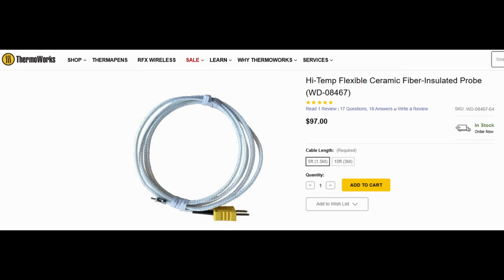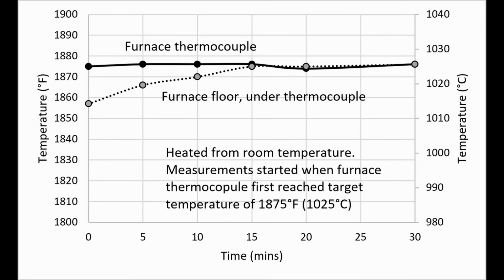And that also can be used to measure the temperature fluctuation throughout the furnace, such as away from the control thermocouple that the furnace is reading. And so you can see that the furnace thermocouple is measuring the same as your secondary thermocouple and be confident that it is functioning correctly. And so here is a chart that I took. I took a bunch of measurements of my even heat furnace with a secondary thermocouple, and I found that the furnace thermocouple would reach the temperature, but at the floor of the furnace, it would take some time for the furnace to fully equalize and reach the same temperature as the furnace thermocouple, which was at the ceiling of the furnace. So that was interesting and useful. Most of the time, everything is good, and if the thermocouple is functioning, it's reading approximately the correct temperature. But checking with a secondary thermocouple, you can see, is everything operating how it should?